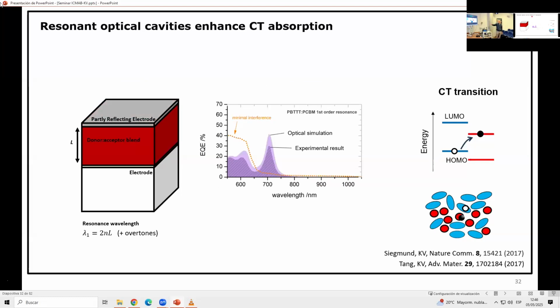And the way to do it was rather simple, I would say. Instead of using this transparent top electrode, you use this partly reflecting electrode. It just means a thin metal, which is half mirror, but still also half transparent. So very simplistic, if you don't think about wave optics, it's basically a box with 2 mirrors. So once the photon is in, it keeps bouncing in between the 2 mirrors until it's absorbed.